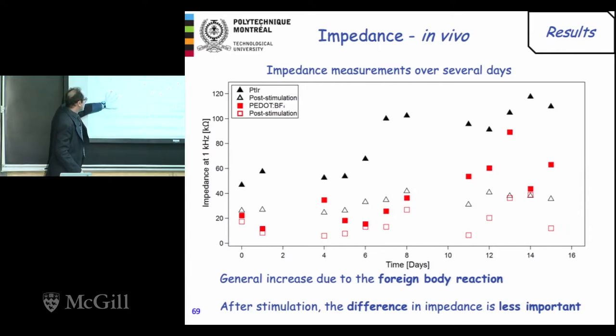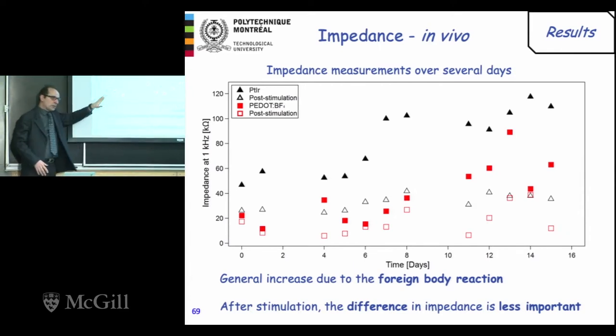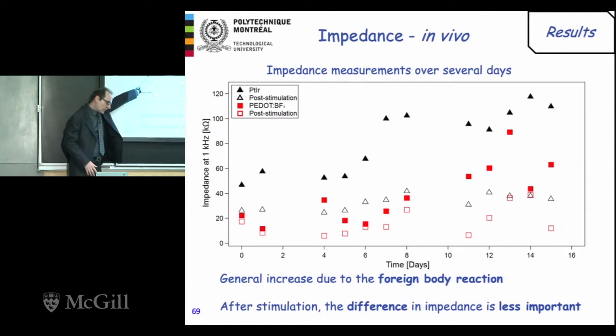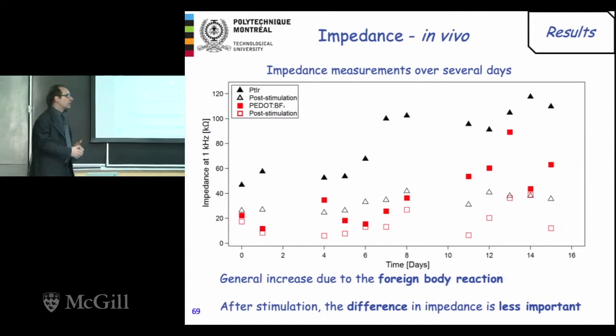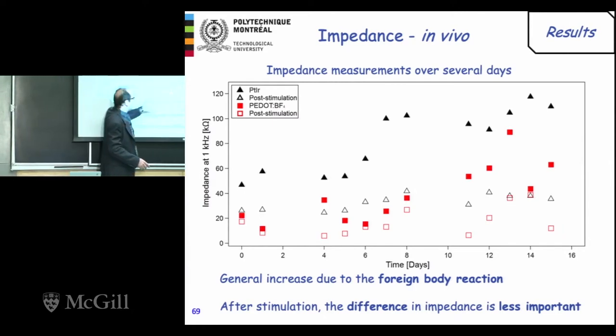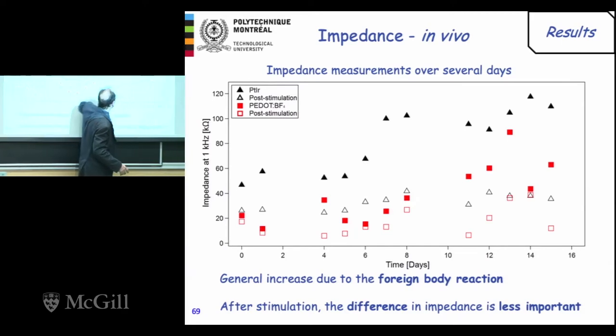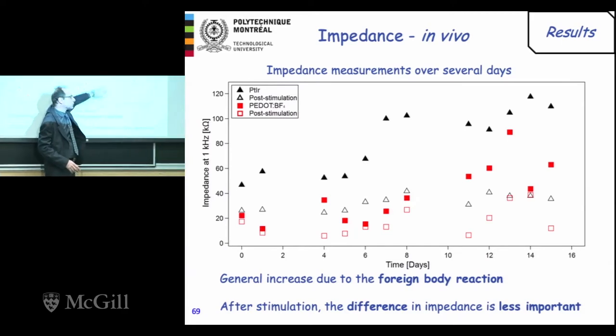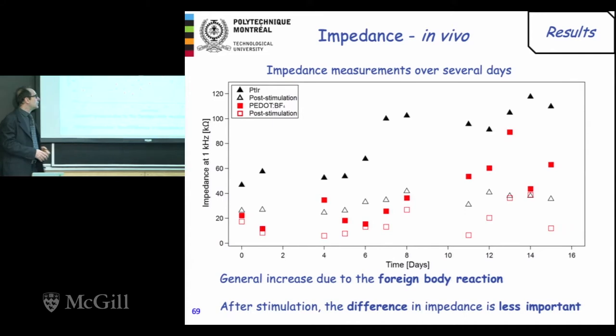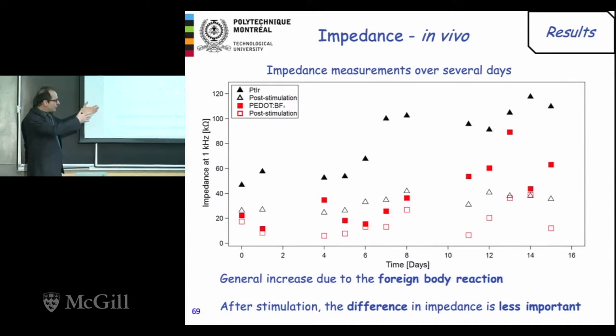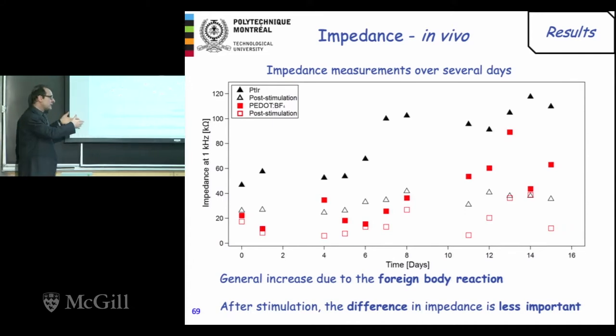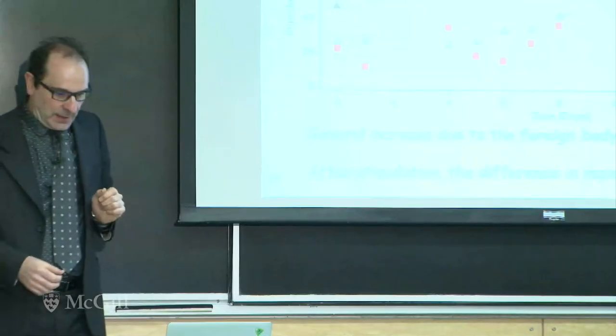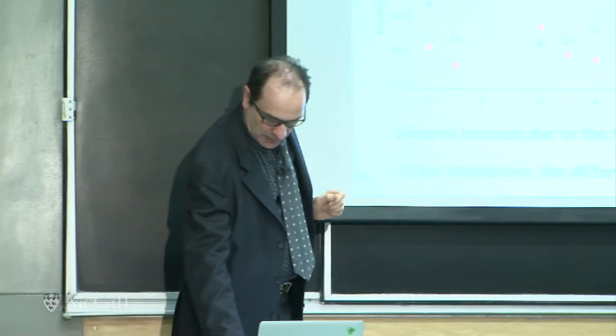You can see that the impedance of the conducting polymer electrode is always lower than the platinum electrode, which is something you want for implanted electrodes. But if you look at what happens after a certain time, it's not really clear. So we need to have higher statistics to prove that these electrodes are better. But we were successful in implanting these electrodes in the first animals. OK, I will stop here.